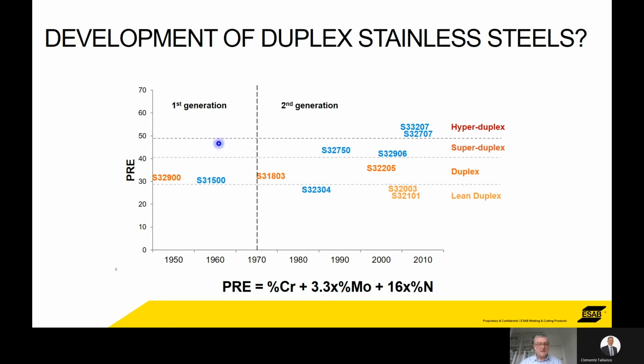What we have on this graph here is this magic number called PRE, which is pitting resistance equivalent number. So you put the composition of the alloy into this equation and come out with a number. So the amount of chrome, molybdenum, and nitrogen. You come out with a number, and this PRE number is a measure of how resistant the alloy is to pitting corrosion. Pitting is a very dangerous, difficult method of corrosion because it's not really predictable.